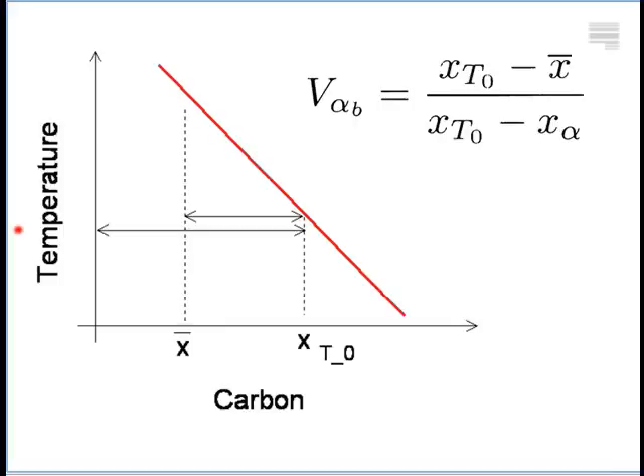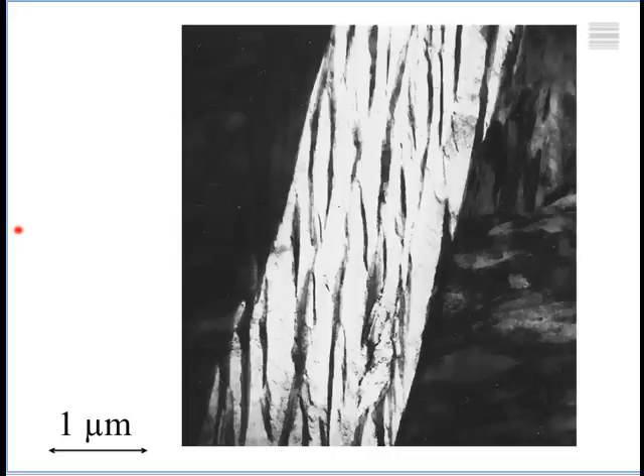Okay? But if I look at that equation, there are possibilities. If I reduce the carbon concentration here, then I will get an increase in the volume fraction of bainite. If I can manipulate this curve by adding other alloying elements so that I increase the T0 curve to larger concentrations, I can also increase the volume fraction of bainite. But to get a structure which is so beautiful, with just plates of bainitic ferrite and nice thin films of austenite, is very easy. To get the right properties, it's not. And I will explain to you how we did this for the OCTG pipes.